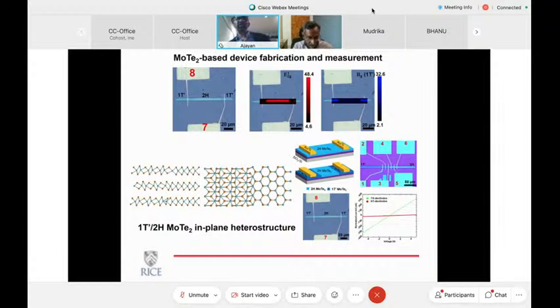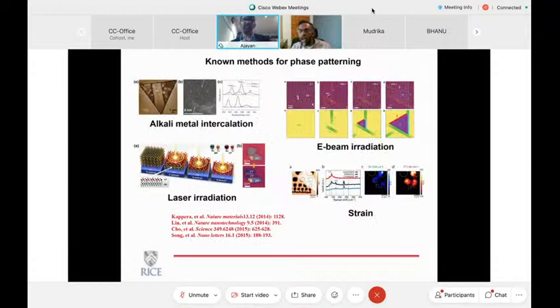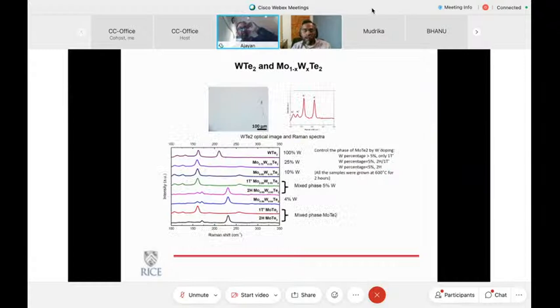But we wanted to do this in a more systematic way so that you can precisely define where the metallic phases form. One of the ways of doing this is actually to go and change the 2H phase into a 1T prime phase by laser radiation or some strain engineering or intercalation. There are lots of ways people have shown this and published in very big journals. But even all these are essentially time consuming and not very scalable. So what we decided to do was to see if you could actually do this during growth itself.